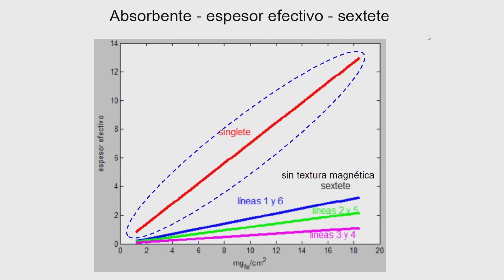But one of the things that happens is that you increase the amount of iron in your sample. This is here as milligrams of iron per square centimeter. Then you see the effective thickness increases very much, but it depends, of course, if you have a singlet or a sextet, because in a sextet the signal is much more distributed, and then this effect is a little bit less restrictive. And in the case of a sextet, it depends on which kind of line we are looking at, because usually the lines 1 and 6 are, in the case of a sextet, I mean magnetically split, the most intense ones. If you don't have polarization in your sample, then these lines are more sensitive to this effect.